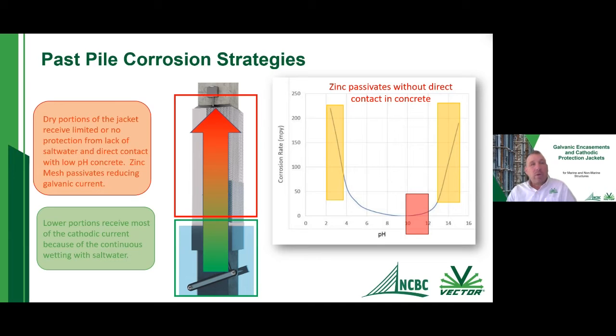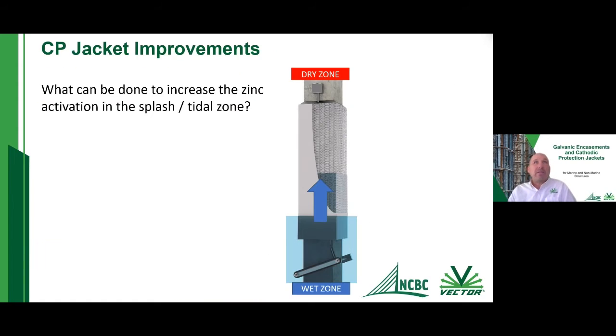And when you have zinc that's embedded in concrete, you can see on the right side that zinc only starts to corrode either in a very, very high pH environment or a very, very low pH environment. So when we have our zinc embedded in this concrete, the zinc does not want to corrode, and that's why we're relying on that salt water. We're relying only on that salt water to activate the zinc in this case.